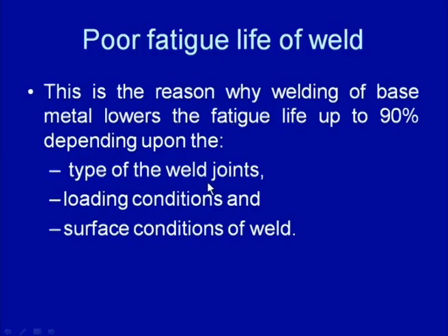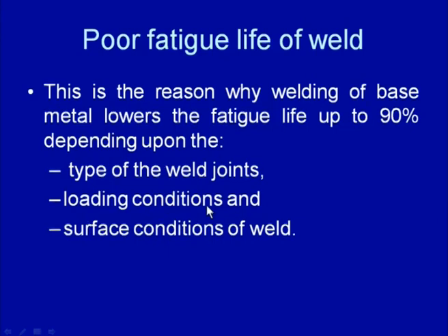So, the extent of the reduction in the life of the component is governed by the type of weld joint which is being used, like butt joints offer better fatigue life than fillet joints, the loading conditions, whether it is tensile or compressive, and the surface conditions of the weld, like the presence of ripples, discontinuities and other forms, and the residual stresses at the surface of the weld. So, due to these typical features related with the weld joints, the fatigue life of the weld joint is found to be significantly lower than their base metals.